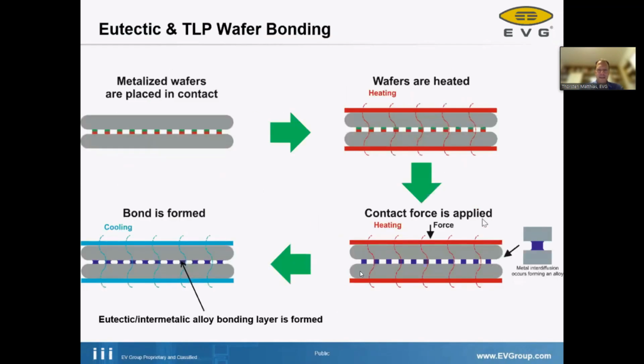Okay. Again, the cartoon is very similar to what we have seen for the metal thermocompression bonding, but the main difference is, in this case, during the bond process, I go shortly through a liquid metal phase, which means with eutectic bonding, it's a lot easier to deal with gaps in your interface. In other words, with metal thermocompression bonding, you have to take a lot more effort in order to avoid having gaps in the interface prior to the bond.